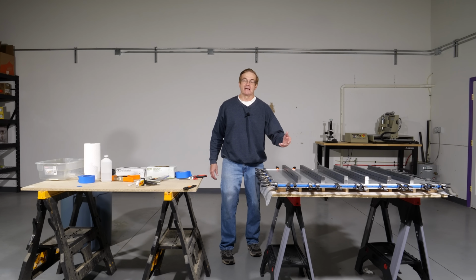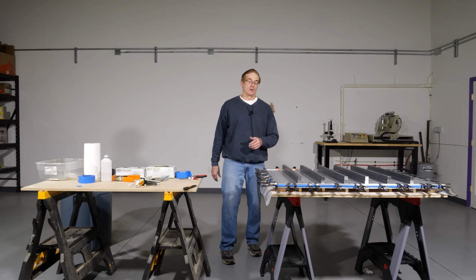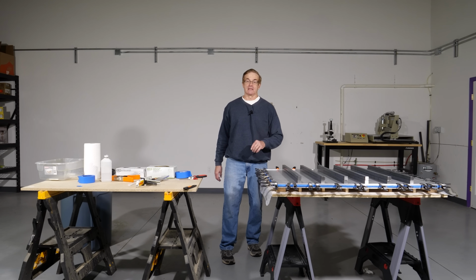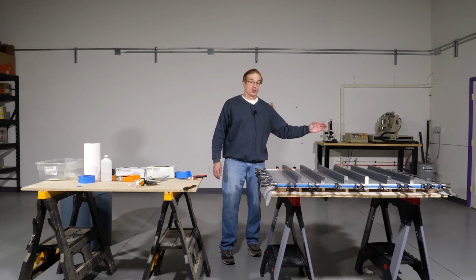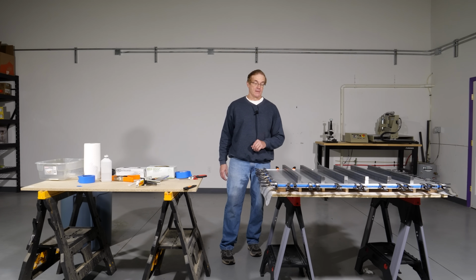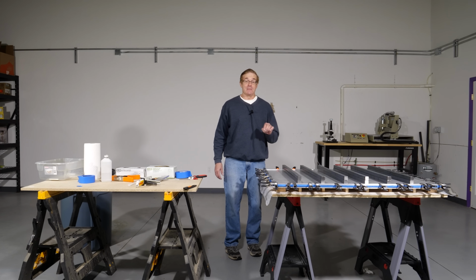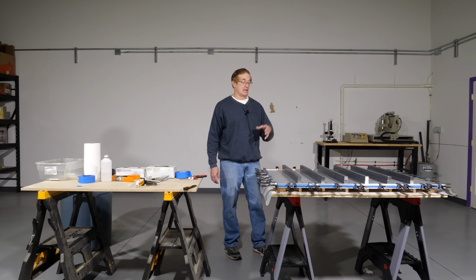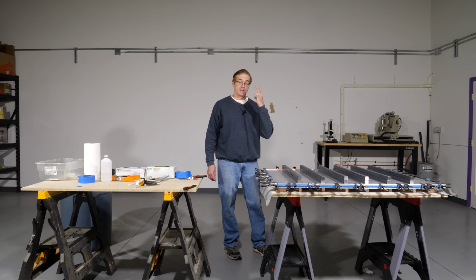Aluminum doesn't absorb epoxy like wood or fiberglass, and so you really don't need very much in order to coat a surface. We wanted to be very generous on the outside because any kind of a leak, it'd be a disaster. So we really wanted to make sure we had a good epoxy seal. So now we're going to leave this 90-minute working time epoxy a couple of days to really harden up. Then we're going to fill this thing up with water, cross our fingers that we don't get any kind of leakage, and then we'll move on to the next stage, which is to put the super coating on it.